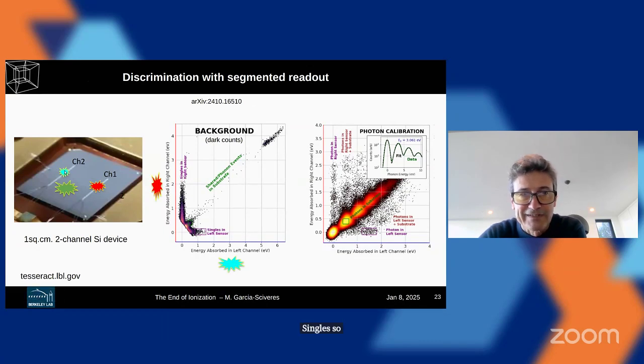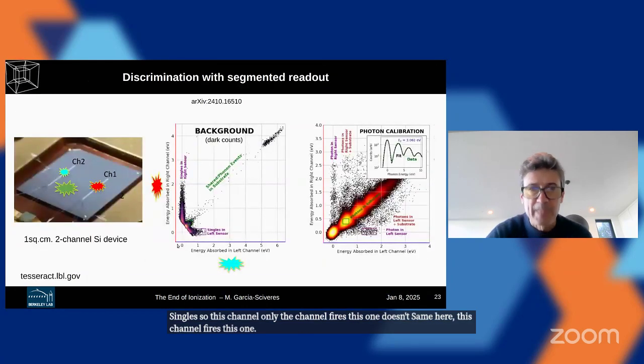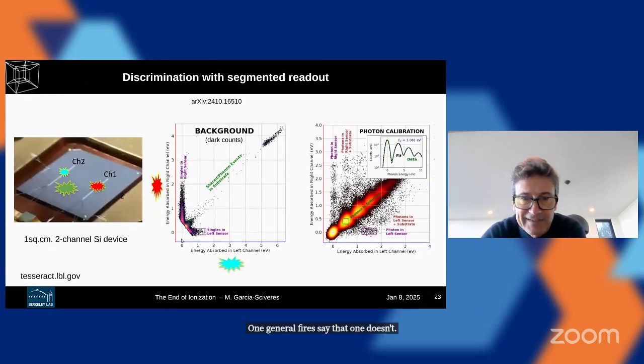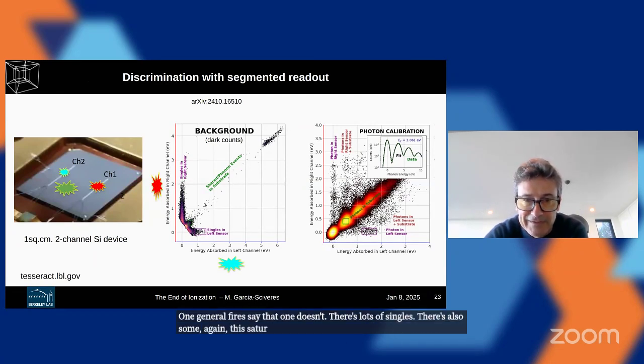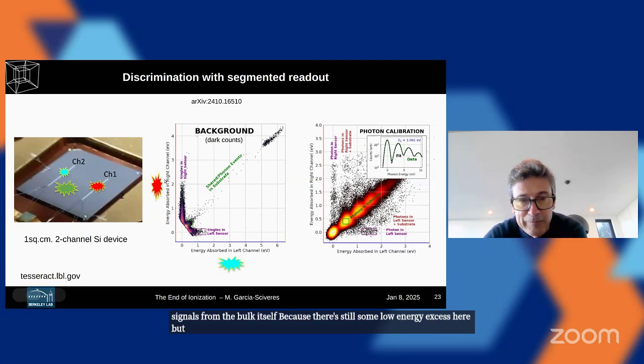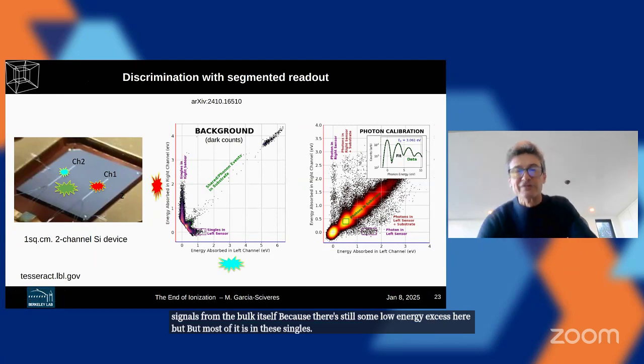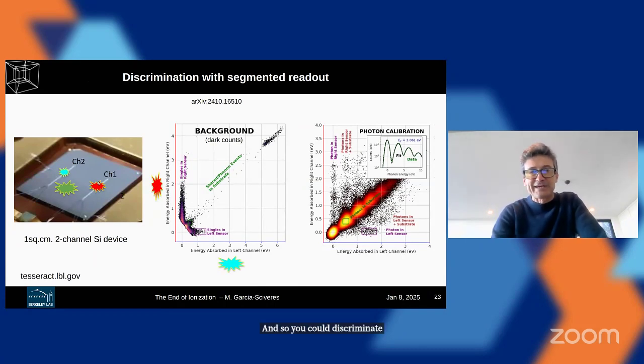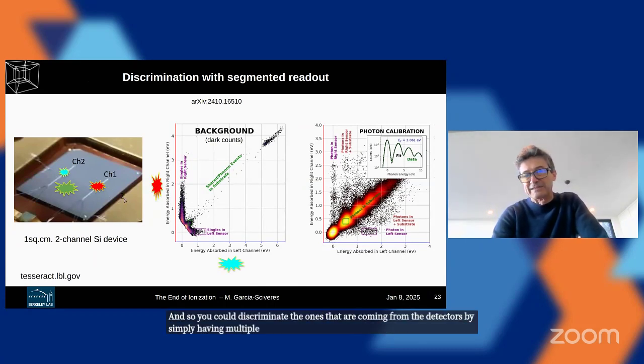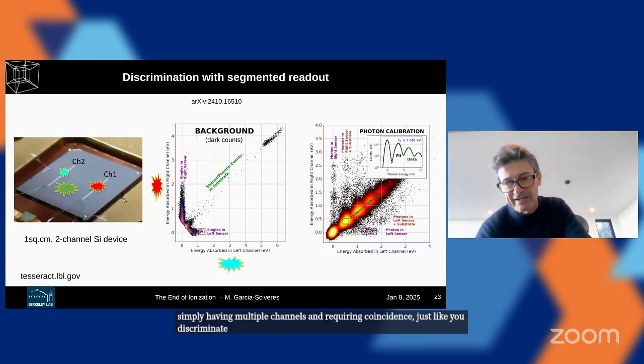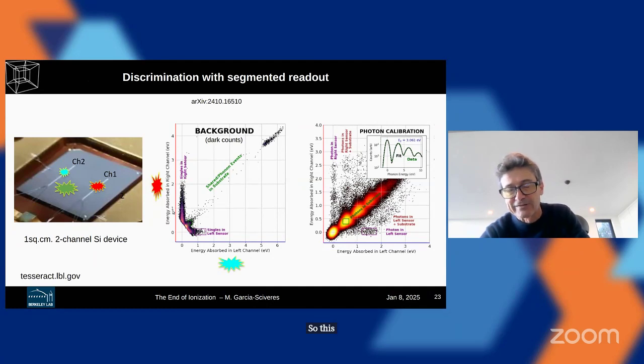So in this channel only, this channel fires, this one doesn't. Same here, one channel fires, the other one doesn't. There's lots of singles. There's also some saturation here, but then there's also some coincident signals from the bulk itself, because there's still some low energy excess here, but most of it is in these singles. And so you can discriminate the ones that are coming from the detectors by simply having multiple channels and requiring coincidence, just like you discriminate dark counts in photomultiplier tubes and SiPMs, right? You require coincidence. So this works for quasi-particle assisted detectors.